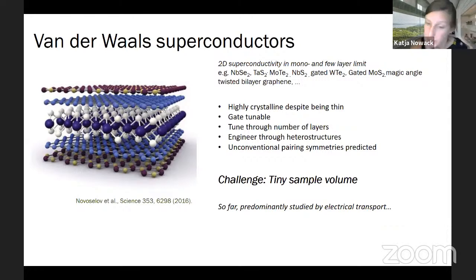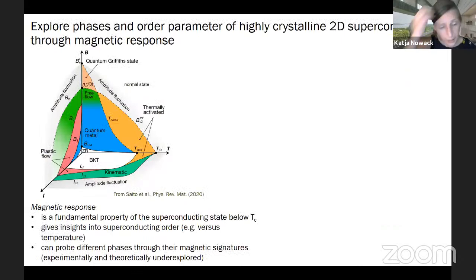And so a very basic measurement that you want to do on a new superconductor is measure its superfluid or diamagnetic response. But for this class of superconductors, you really can't do that using a bulk magnetic property measurement system, just because the samples are atomically thin and at most laterally maybe tens of microns in size, but not bigger. And so predominantly these have been studied in electrical transport.